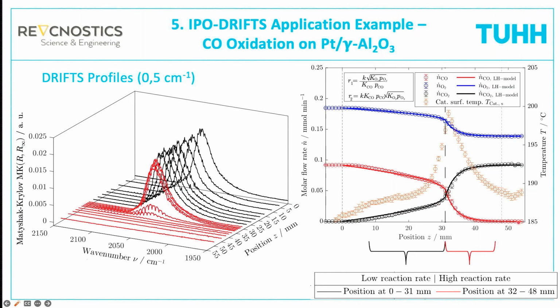And you can see now how the CO is consumed at the platinum surface. And when all the CO in the gas phase is gone, then there is also no more CO on the surface of the catalyst. You see that the isopotential correction works very well if the reaction rate is not too high, and only here in this zone where you have a very steep gradient, a very high reaction rate, then you see some leftovers from the gas phase.